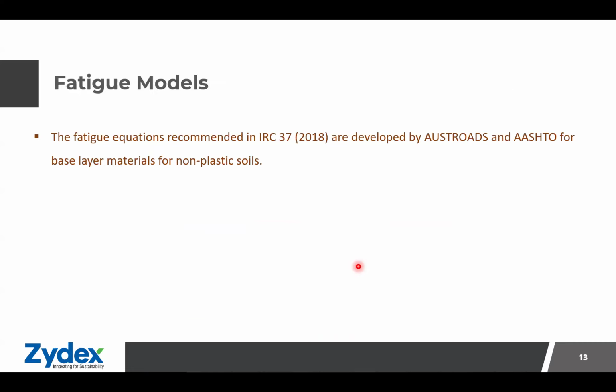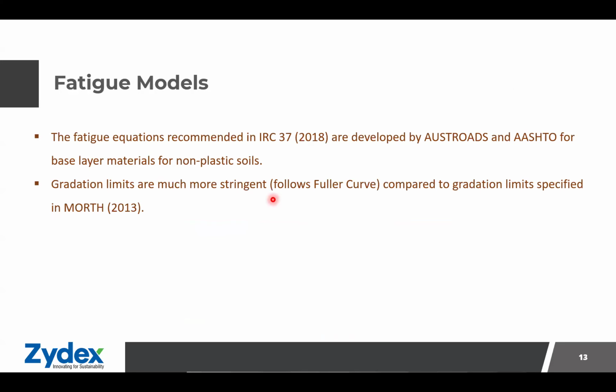Further, talking about the fatigue models, the fatigue equations recommended in IRC 2018 are developed by Austroads for base layer materials for non-plastic soil, as indicated previously also. Their gradation limits are more stringent. They follow the Fuller curve, and the allowable limits are within a very narrow range. But the specifications laid out in MORTH are quite wide.